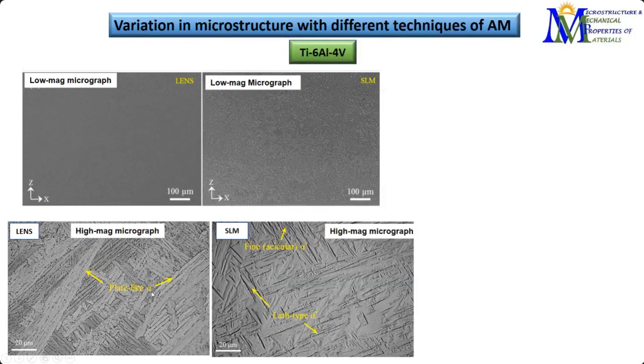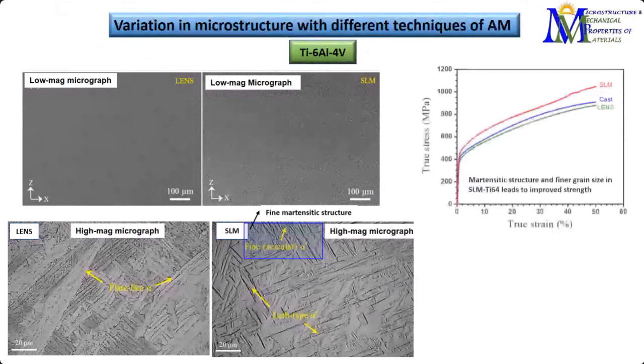Whereas if we look into the higher magnification microstructure, we see that in fact SLM leads to formation of a martensitic structure - this fine acicular alpha prime is nothing but martensitic structure, and martensite structures have a lot of other benefits. It's usually much harder compared to the normal alpha phase.